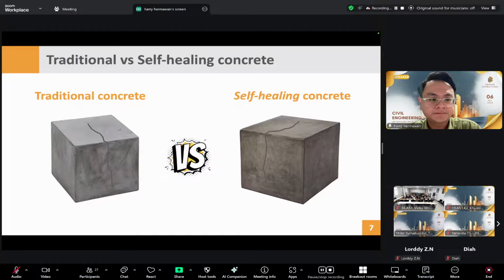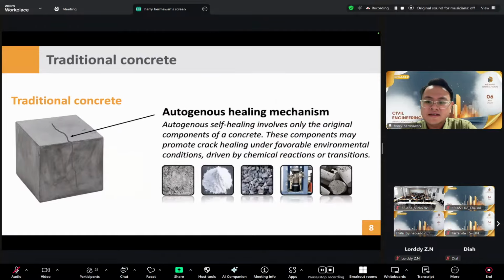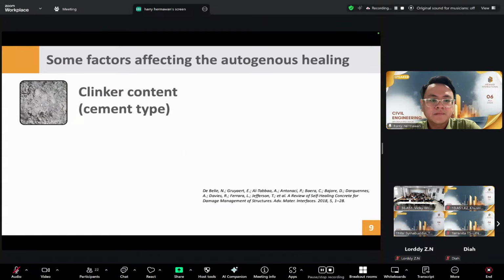Let's have a look much deeper. The autogenous healing mechanism is the mechanism which is derived from the original constituents of the concrete. This component promotes crack healing only under favorable environmental conditions and is mainly driven by the chemical reaction of the raw materials. So what are some factors affecting this autogenous healing mechanism, particularly in traditional concrete? First of all, it's the clinker content or the cement type. The clinker content in relation to the cement type determines the supply of calcium ions and subsequently the ability to develop precipitation products.